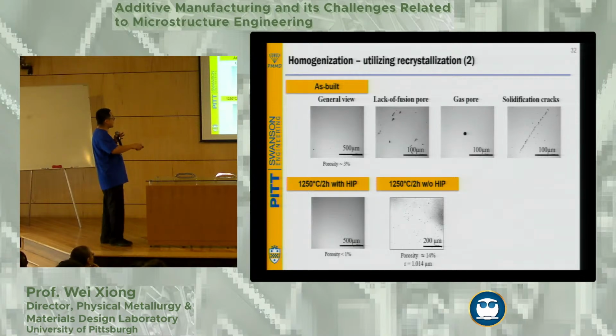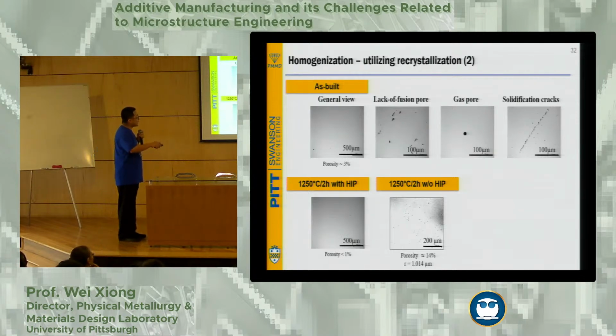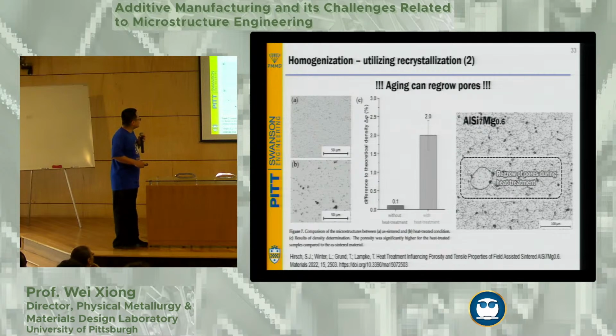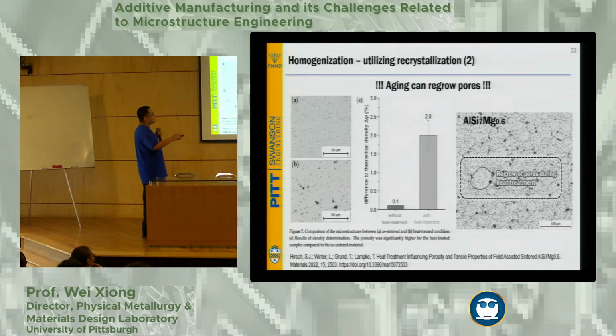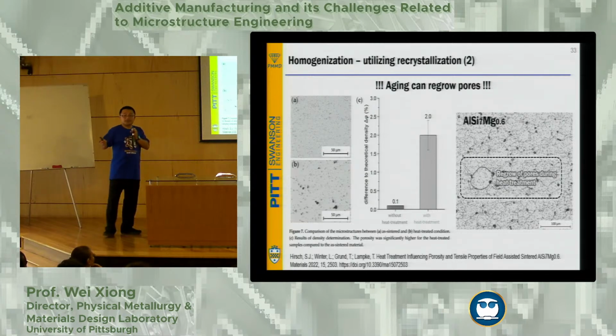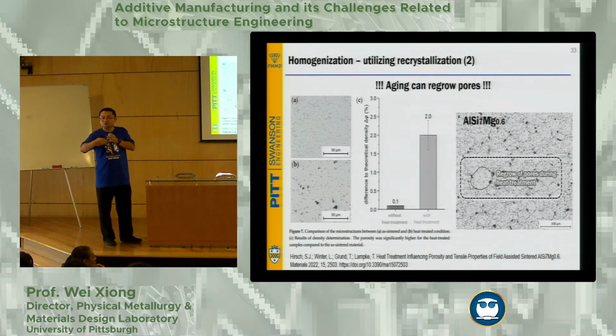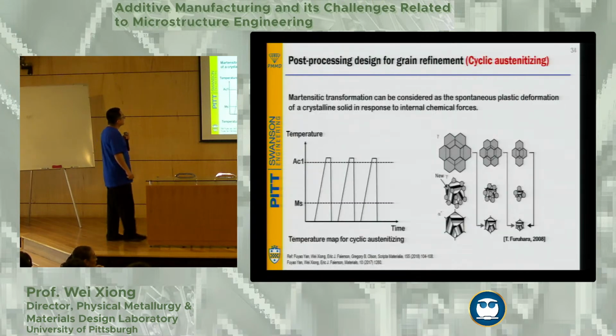So what we need to do is actually introduce a hipping process. If you don't have hipping, hot isostatic pressing, then the pores will become another issue to retain high strength for this alloy. So aging, particularly, can grow the pores. This is another example you can find with aluminum alloys. So there are a lot of trade-offs in how you design additive manufacturing with heat treatment and processing. And of course, you have a lot of degrees of freedom to introduce a good design for the material as well.